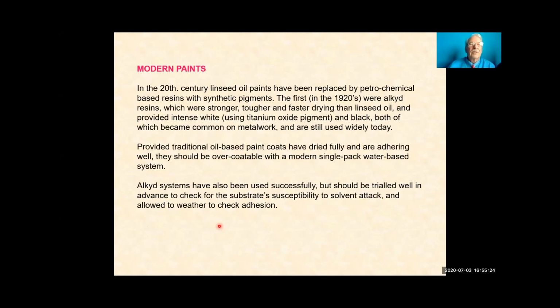They're all now petrochemical-based resins. The first ones were the alkyd oil resins from the 1920s and 30s, and they are very common still, single pack. The advent of intense white, that was titanium oxide, and black were both concurrent with the alkyd paint. So you won't usually find pure black and pure white much before the 1930s.